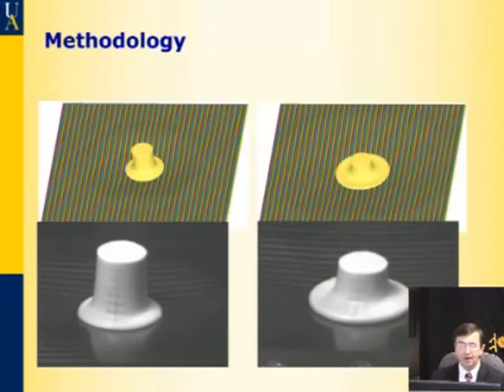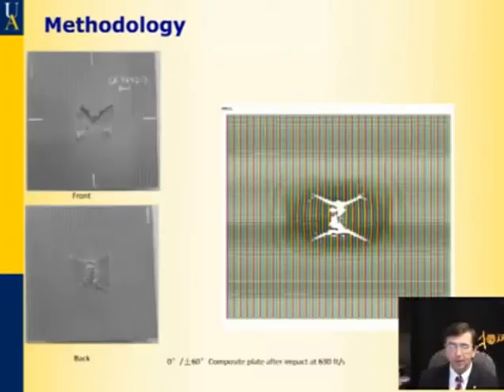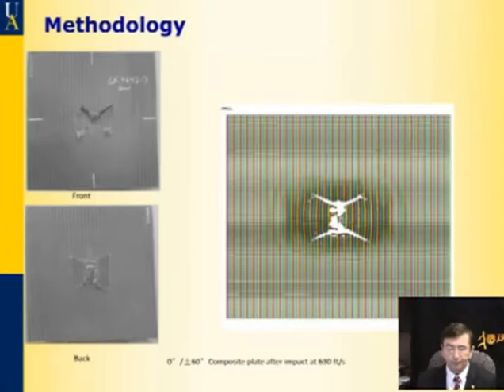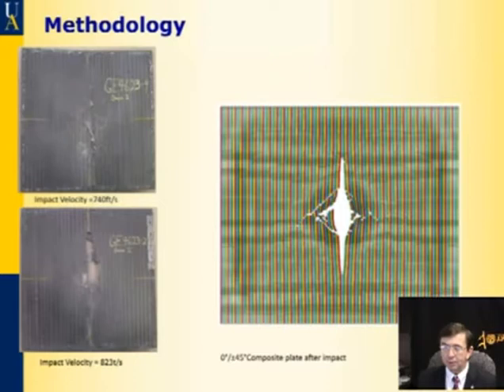Each snapshot represents a comparison between real and virtual impact experiments. It is also important to predict the damage modes. In the case illustrated here, a butterfly damage shape agrees with the experiment for plus-minus 60-zero tri-axial braided composite. Once the model properly represents reality, we gain confidence that we can obtain deformations and failure shapes for any similar material. For example, if we change fiber architecture from 60 to 45 degrees in the composite, a different damage shape is produced, which can be correctly predicted using our model.